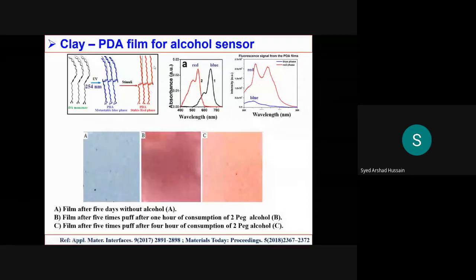One is the blue phase and one is the red phase. An interesting thing is that these two phases have unique spectroscopic properties. For example, this is the absorption spectra. This is for the blue phase. This is for the red phase. This is again fluorescence. For the blue phase, you see almost no fluorescence. Red phase, very high fluorescence.